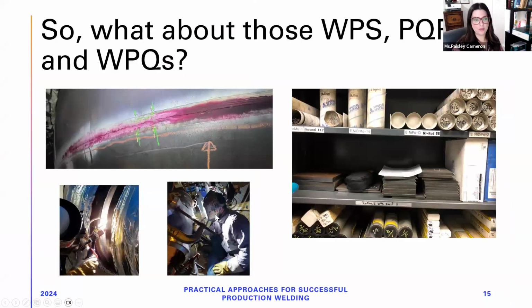So what about those weld procedures, PQRs and WPSs? Here's a really good example of a specific job that followed the weld procedure, had the proper PQRs, had the appropriate welders, and still had cracking. As you can tell, there's a difference of thicknesses on these two in particular, and this piece of equipment operates under vacuum. So that's where the selection of your consumables becomes very important for those services. And just because you have a weld procedure doesn't necessarily mean it's going to be appropriate for that specific job. Some other pictures of actual welding being completed.